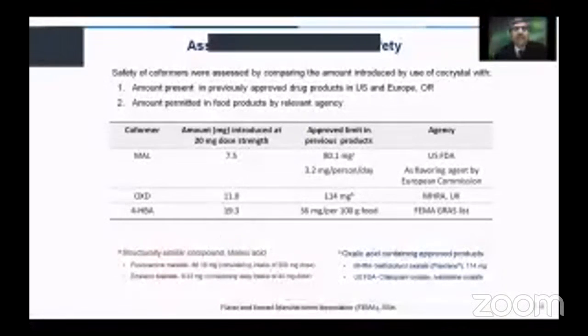And these were then evaluated in terms of their quantity that is going to be present in 20 milligram strength of rivaroxaban. And then we evaluated whether they are within the limits that are existing in the approved products or in certain other guidelines of the regulatory agencies. As is very clear, for malonic acid, the quantity present in the co-crystal for 20 milligram strength would be 7.5 milligram, whereas 80.1 milligram has already been approved in other products.